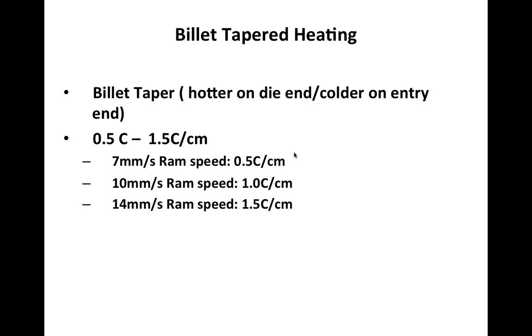Billet taper heating. I think the goal of every extruder is isothermal extrusion. By isothermal extrusion, it means that we would like to have an optimum and stable exit temperature from the extrusion press. If we start with a uniformly heated billet, the only way to get a stable and uniform exit temperature is by varying our ram speed.